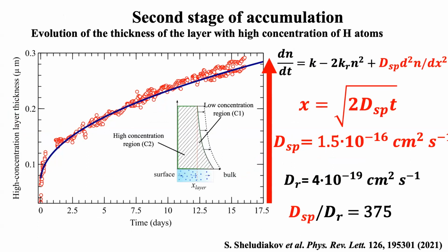After that, we consider that this should be diffusion, one-dimensional diffusion. So the solution should be a square root of 2 spatial diffusion multiplied on time. This solution is shown here like a line, and from this fit, you can determine the spatial diffusion. And this is 10 to minus 16.